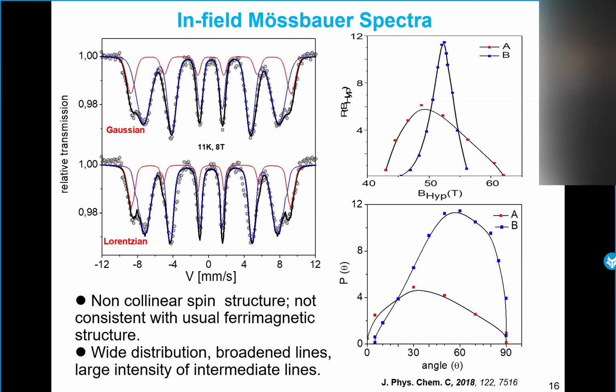For this kind of hyperfine structure, we need to correlate the effective field with the spin canting in order to obtain the hyperfine field. So we fit that using two different methods. In the first method, we introduce two subspectra corresponding to A and B sites, but using a Gaussian line. That allows us to have directly the mean information about the hyperfine parameters. The fit is okay, but it is not physical because the Mössbauer line is a Lorentzian line. So now, starting from the mean information obtained here, we can do the distribution of the effective field with the spin canting on each site, and we obtain some correlation. And from that, we obtain the distribution of the hyperfine field.